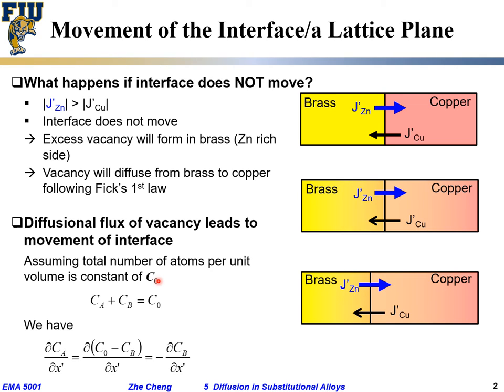Okay. And then we would have this relationship. Do you see that? The concentration gradient of C with respect to my moving coordinate. CA is C0 minus CB, right? CA is C0 minus CB from here. And the C0 is what we assume to be constant. So do you see now we are going to have a negative sign of the partial differential of CB versus X prime? Do you see that? From here to here. Because CA and CB added together become a constant number. Make sense?